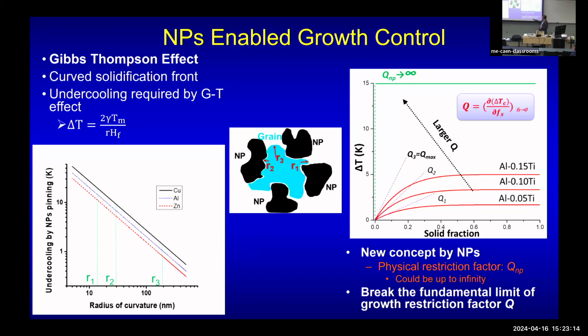More important is that once a grain starts to grow, the nanoparticles restrict your growth. When a grain starts to grow, the nanoparticles just pin down this growth. If you want to grow over them, you need more undercooling. For a 20 nanometer nanoparticle, you need almost 10 degrees C more undercooling, otherwise you will not grow. So this is a significant restriction factor by nanoparticles. This is the physical restriction.